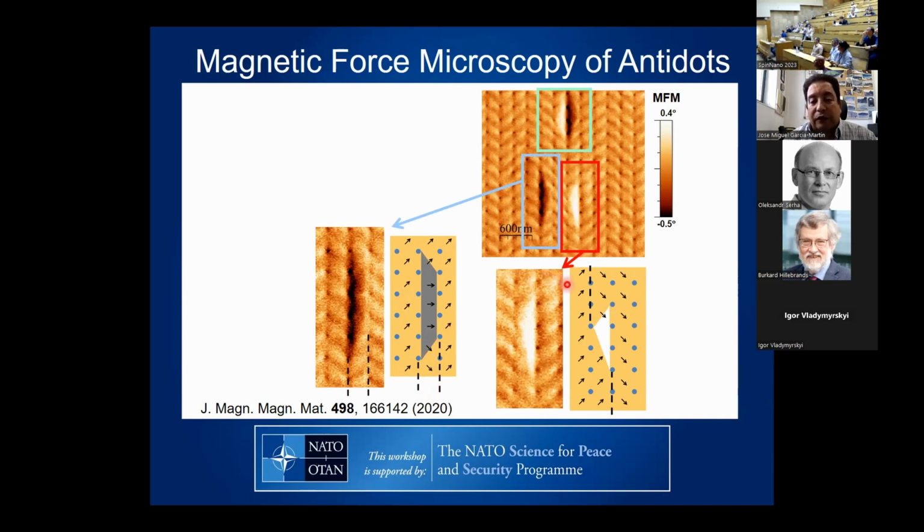If we now focus our attention on the bright region, you can see that this is the scheme. Again, we have two low energy superdomain walls that end where the bright region starts. And in this case, we have a uniform magnetization on the left or on the right. So those regions with a strong monopolar contrast are called high energy superdomain walls because they are accumulating a lot of magnetic poles in those regions.